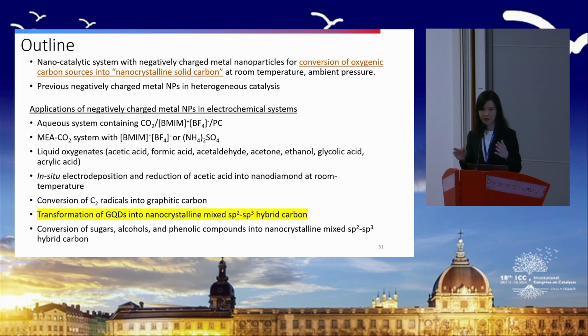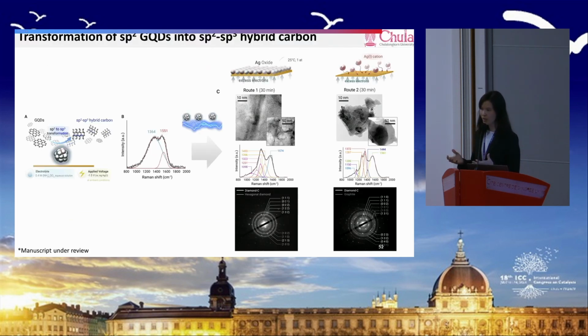And I'm talking about the transformation of the graphene structure towards sp2, sp3. If that's the case, it should work with our commercial graphene. How about trying commercial graphene quantum dots? So now I purchased commercial graphene quantum dots. It has this Raman pattern like this. In this case, there are no other carbon sources. We just have our negatively charged system. We add a little bit of the graphene quantum dots that we purchased, and then apply electricity, and wait for some time.